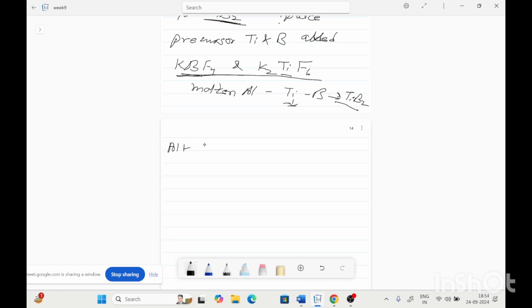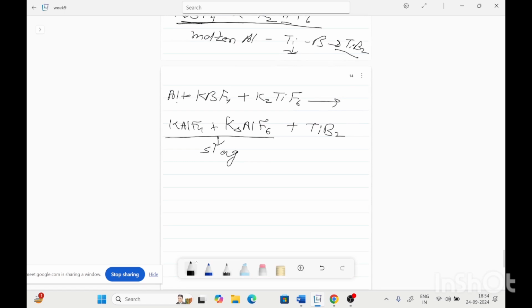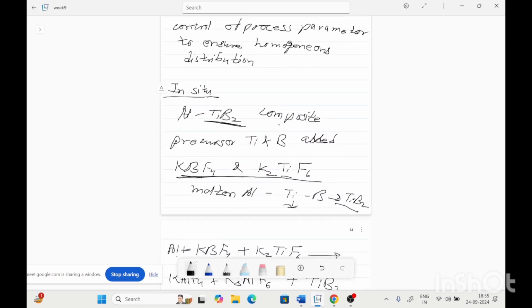The reaction in this process can be written as aluminium plus KBF4 plus K2TiF6, which leads to KAlF4 plus K3AlF6 plus TiB2. TiB2 mixes with the aluminium, and the two salts formed after the reaction are collected in the slag. So the aluminium plus titanium diboride composite is achieved by the reaction of these two salts. This is called the in situ addition of ceramic particles.